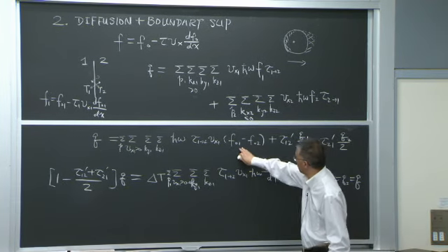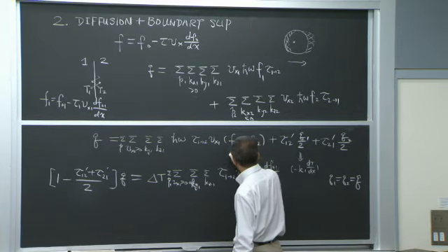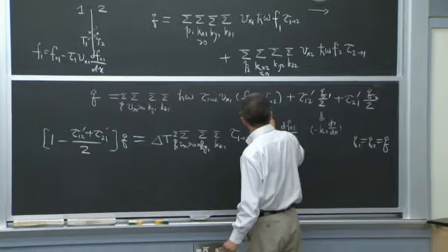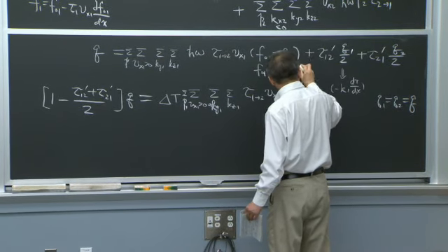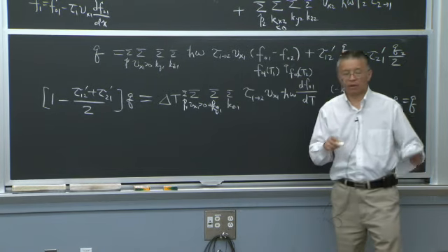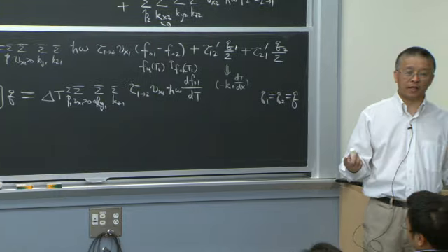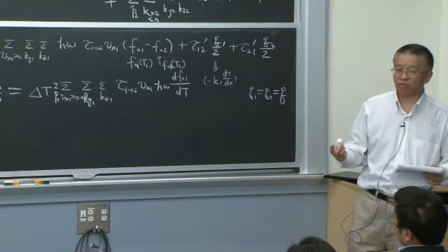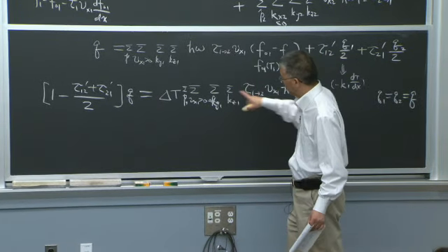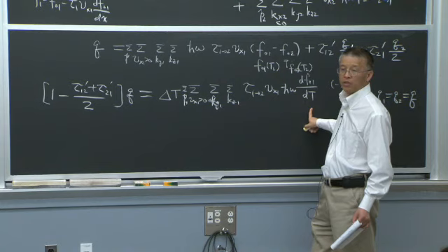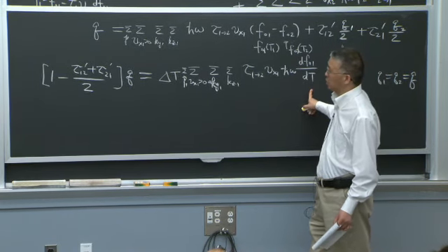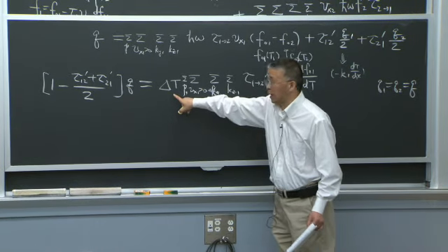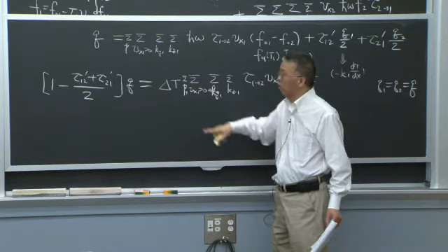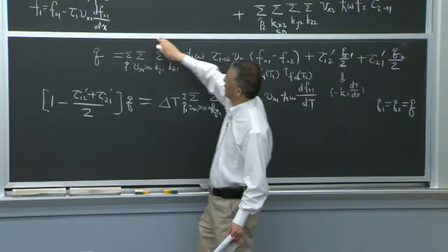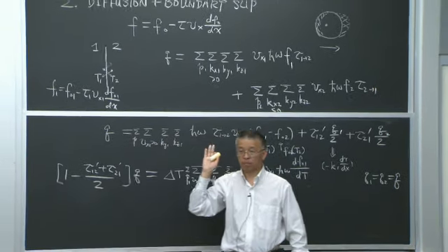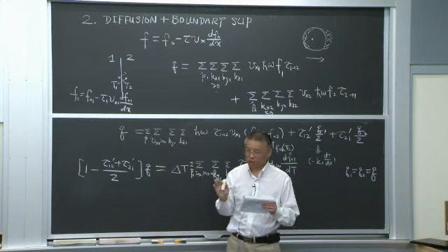So I'm writing basically F01 minus F02. Really what it means is F0(T1) minus F0(T2), because if you think about the Bose-Einstein distribution, it doesn't have anything other than h omega divided by kT, right? So it itself is just to say they write into a differential times this temperature difference across the interface. So you see this derivation shows I have an interfacial temperature drop because of the asymmetry of my distribution on the two sides, and in the zeroth order term, it doesn't cancel.